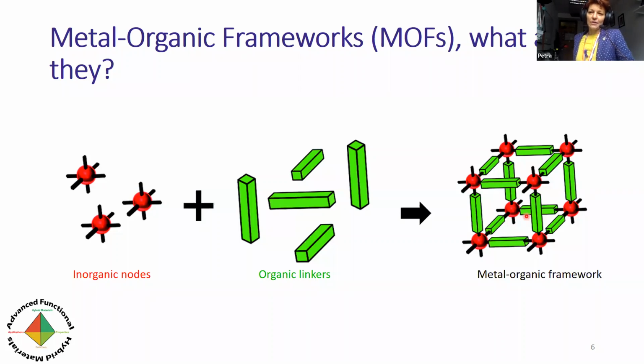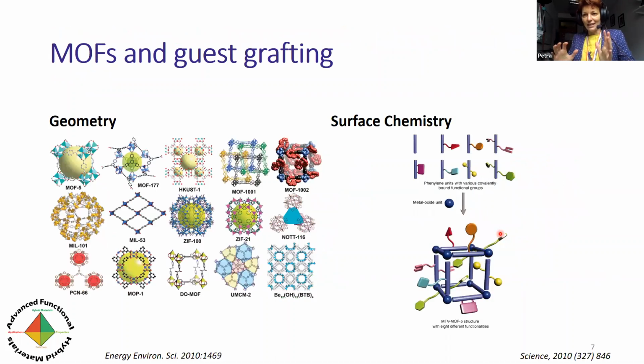Now, it is important to know that there are two main things that will influence that. On the one hand, it's the chemistry of these pores. On the other hand is the geometry of these pores, and particularly, I should also mention, the size of these pores, because they're at the very, very small end of the nanometer scale. So they're typically between 0.3 to 3 nanometers. So it's almost like beyond the nanoscale, if you wish.